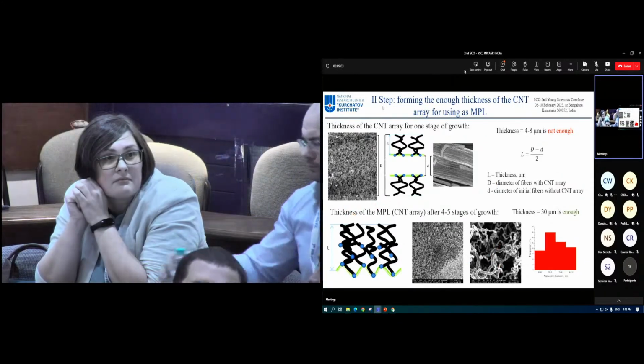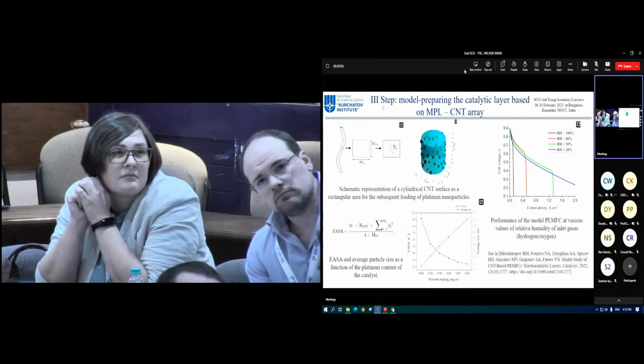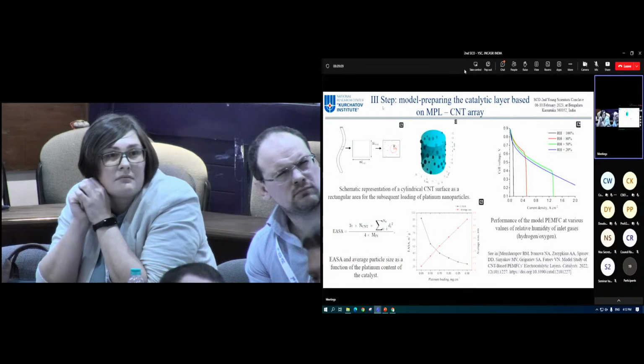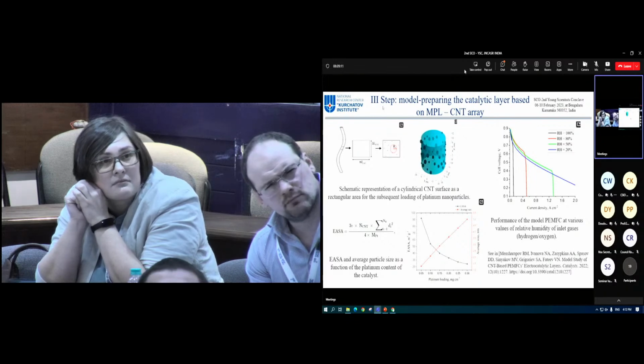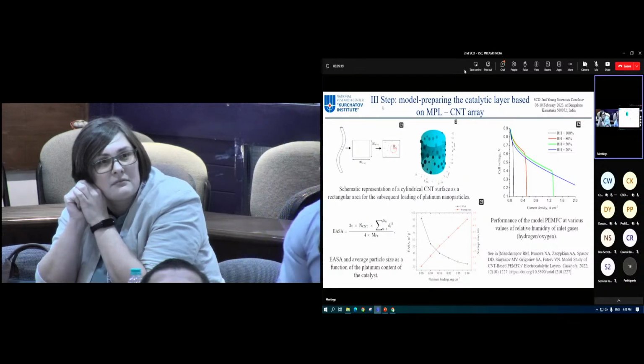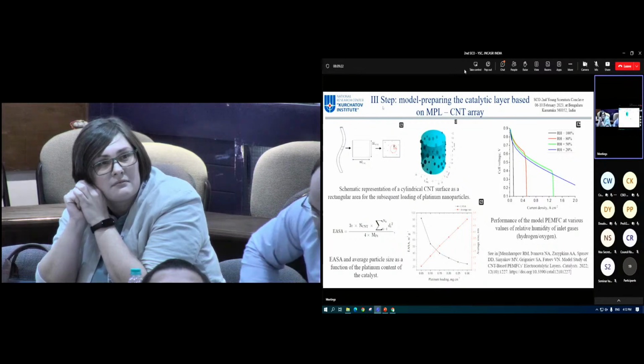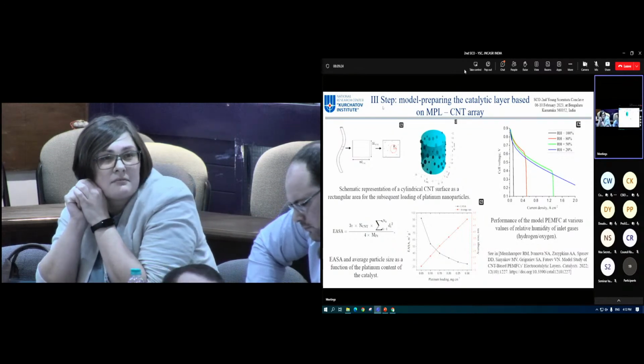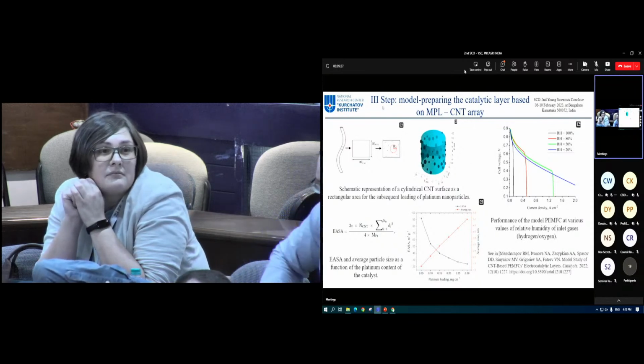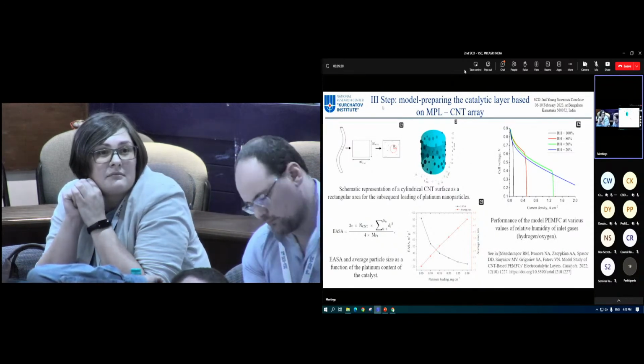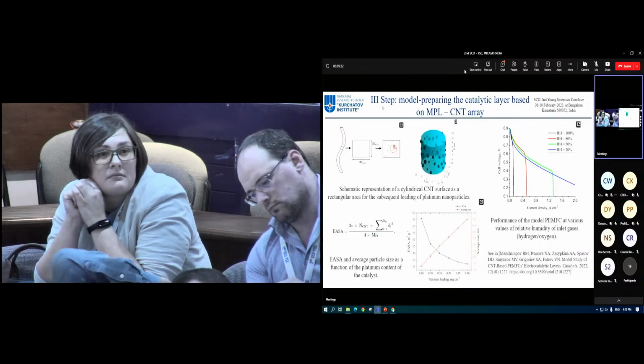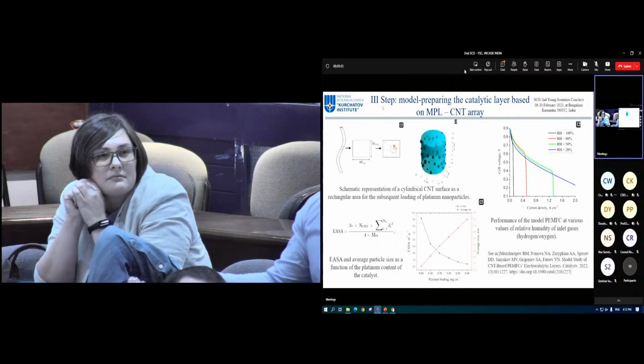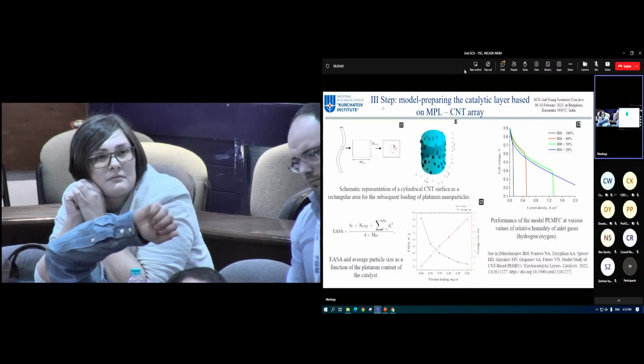The third step is the catalytic layer based on CNT array. To estimate the effect of geometric parameters of a CNT-based support, a semi-empirical model was proposed using a random uniform distribution of particles over the CNT surface. An increase in surface area with decreased platinum loading of the catalytic layers was shown for the CNT-based electrocatalyst. Based on the obtained distribution, the surface area of the electrocatalyst was estimated and further used to evaluate the performance of the catalytic layer as part of a fuel cell.